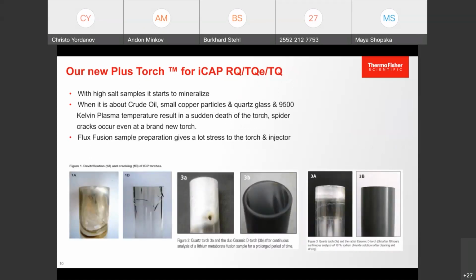So what could happen when you have lots of salts and metals, especially copper? Because when copper hits quartz glass at 9,500 Kelvin, even the smallest copper particles immediately result in such a picture like 1B. It's a so-called spider crack. One little copper particle is enough to kill a complete torch, even when it was brand new in the morning. And also flux fusion sample preparation. So when you have to put more energy into the sample digestion process, this also gives stress to the torch.